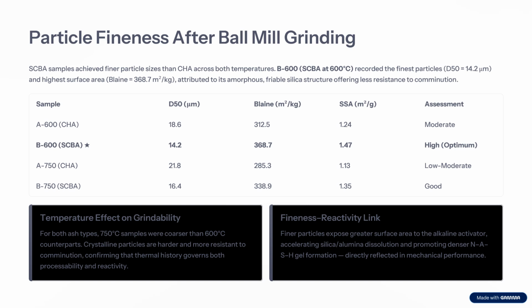comminution. For example, sample A-600 shows a D50 of 18 and a Blaine of 315, with a specific surface area of 1.2, and the assessment is moderate. The highest value was at B600, with a D50 of 14.2 micrometers, Blaine around 368, specific surface area 1.47, and the value is high, optimum. 750 shows a higher particle size, around 21.8, with a lower specific surface area. 750 SCBA shows 16.4 with a lower specific area of 1.3 and can be considered good.